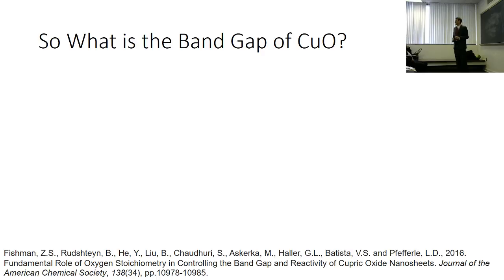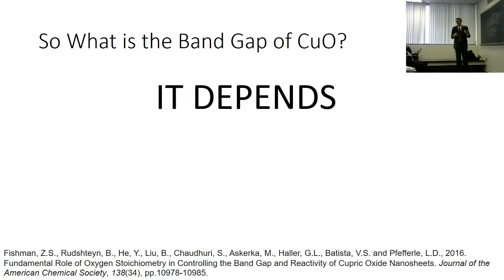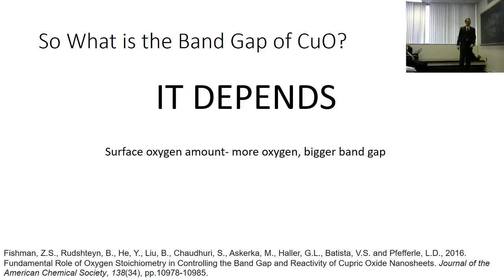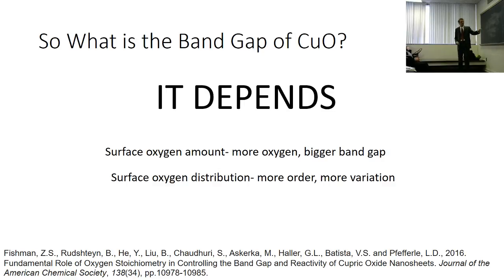So what is the band gap of copper oxide? It depends. It depends on the amount of surface oxygen, so more oxygen, bigger band gap in general. But you also have to consider the surface oxygen distribution, so more ordered arrangements lead to more variation.